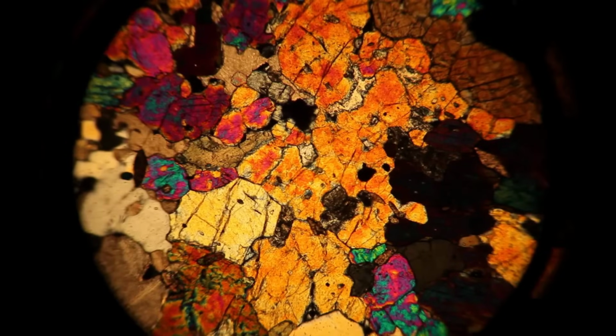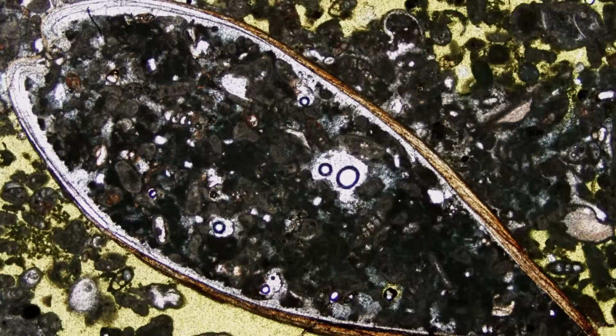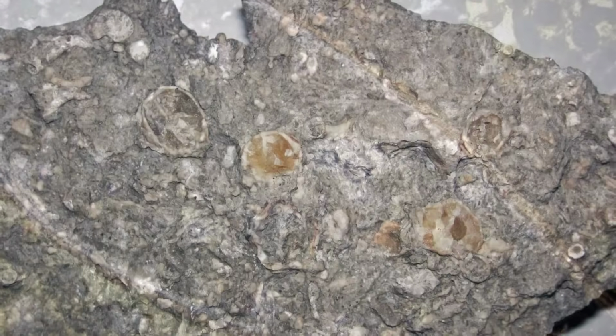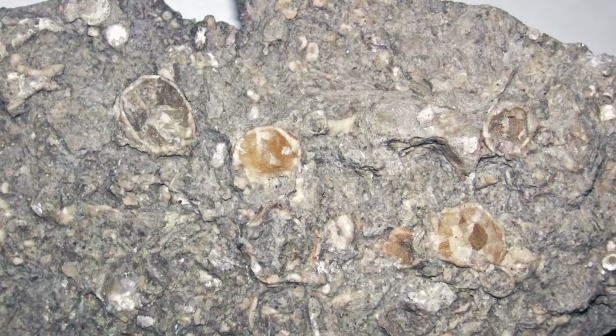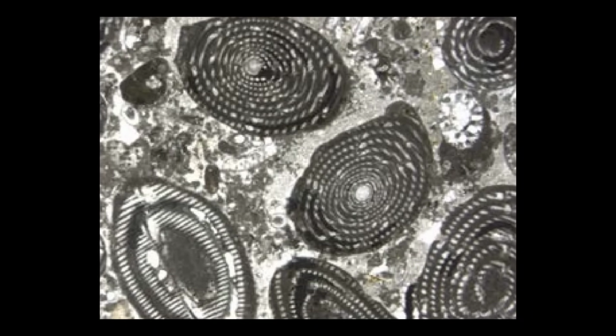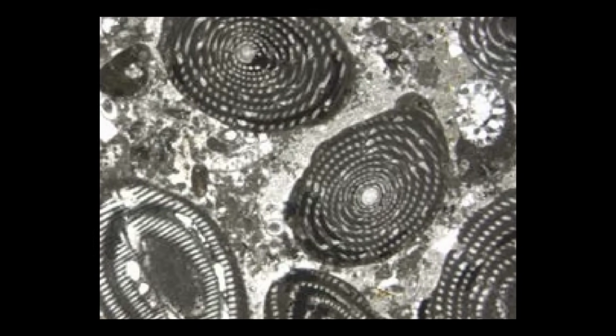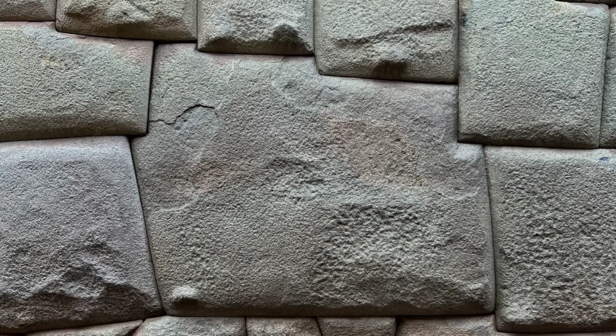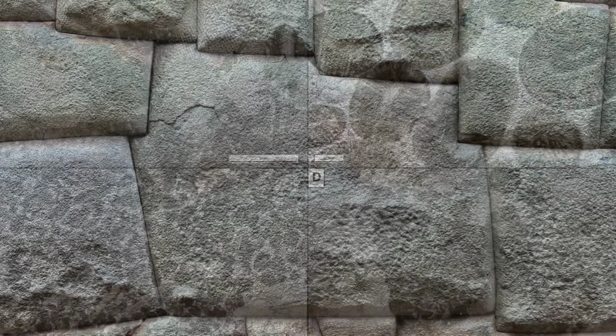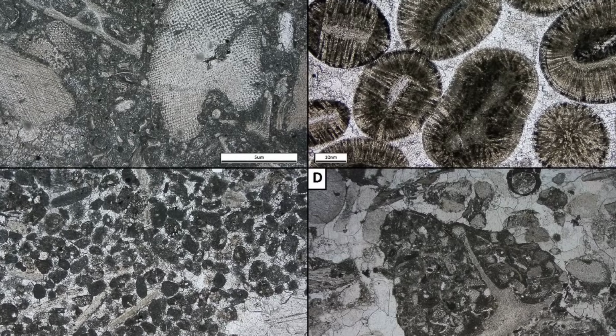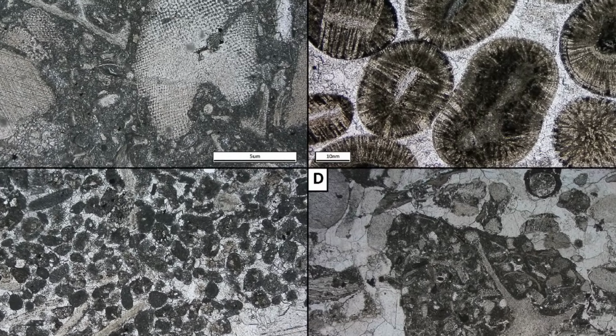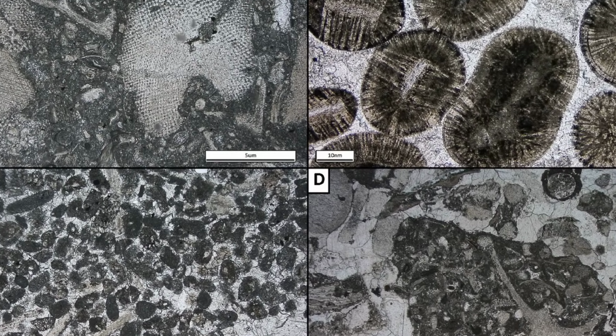In the laboratory, thin section slides revealed the story locked in stone. Quarry samples showed fossiliferous limestone, dense with ancient marine shells and microfossils, clear evidence of a local geological source. Wall specimens, by contrast, told a subtler tale. Most were dominated by microcrystalline calcite, with crystal sizes ranging from 1 to 10 microns.